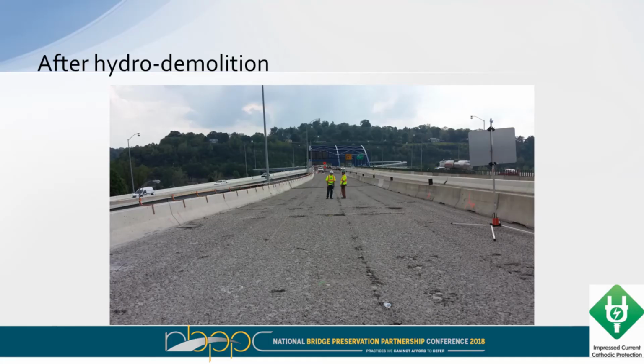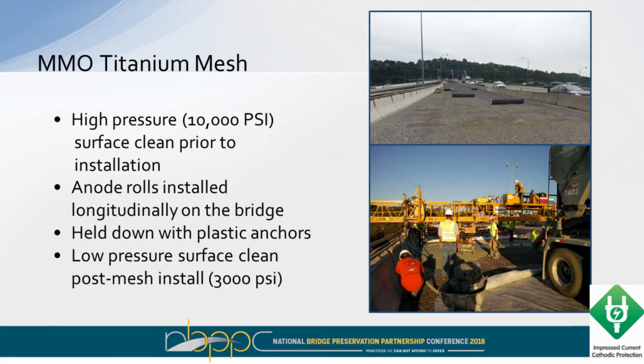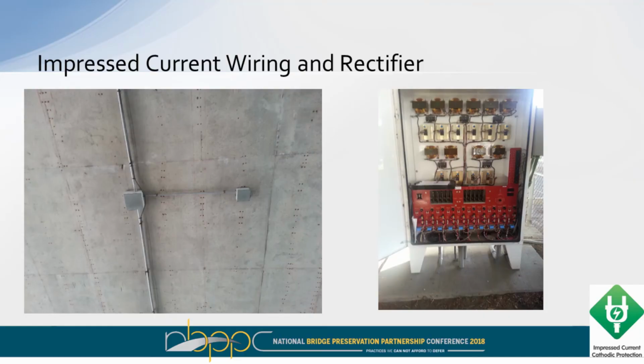So they went to a more modern system in this case where you had hydro-demolition, and then after you prepared the surface, you see the titanium mesh rolls being laid out on the surface, and then that's all hooked up to the electrical system with the concrete overlay over top. And then you see underneath the bridge the wiring and the rectifier, and also remote monitoring.